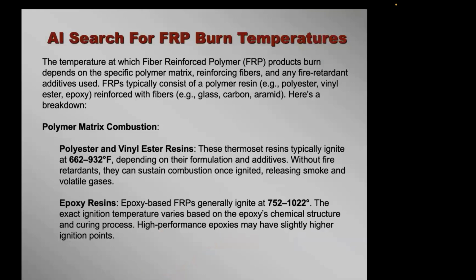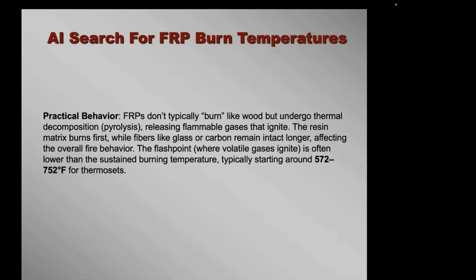So looking at the FRPs, I did an AI search for FRP burn temperatures. Most of these are polyester resins. The polyester and vinyl resins burn between 662 to 932 degrees. Your epoxy resins ignite at 752 to 1022 degrees. But they don't really burn. They go through, like wood does, thermal decomposition. They call it pyrolysis, and this is around 572 to 752 degrees F for your thermosets, which I believe all of them are.